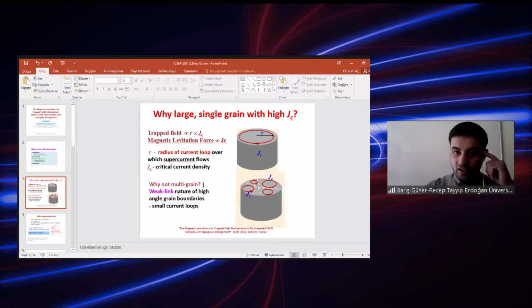Why large single grain? Because there is a good relationship between magnetic levitation force, trapped field and critical current density, and also the radius of the current loop is very important for our trapped field and magnetic levitation force measurements. So why not multi-grain? Because the weak link nature of high angle grain boundaries and small current loops cause low trapped field and low magnetic levitation force.